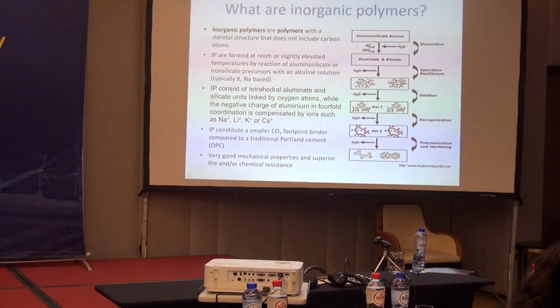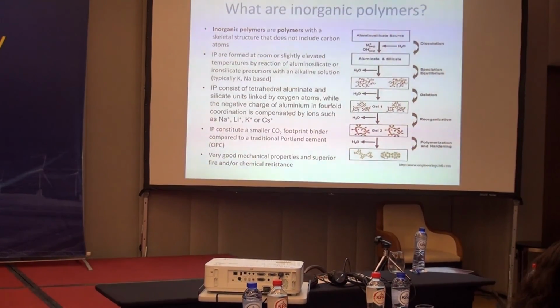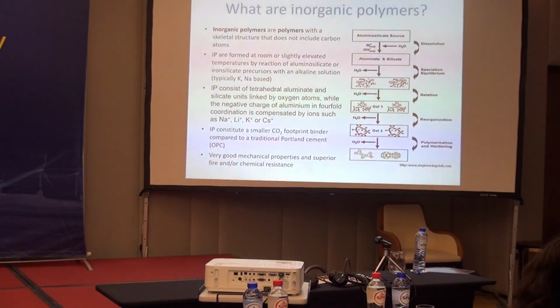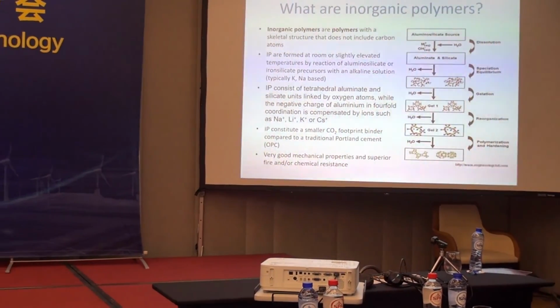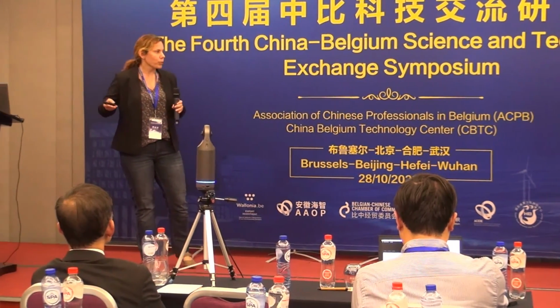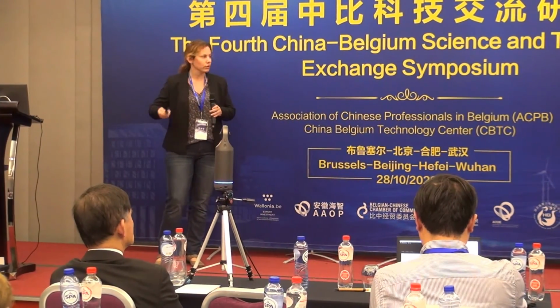Now, what is inorganic polymer? Inorganic polymer is a polymer that doesn't have any carbon in its structure. That's why I call it inorganic. And it's made by dissolving alumina silicates or iron alumina silicates in alkaline environment. Then there is some gelation, polymerization, and hardening. And like that, we create a binder. So with this binder, all the reactions happen at room temperature. So we have a significantly lower CO2 footprint, and we end up with a material that has quite good mechanical properties, and compared to cement or concrete, some superior properties like fire or chemical resistance.